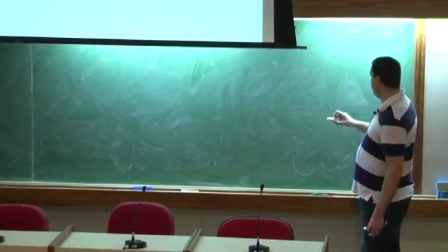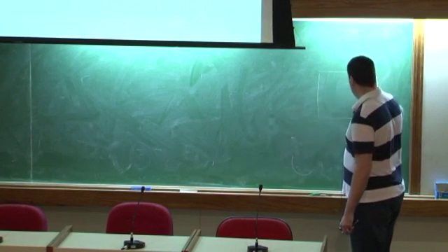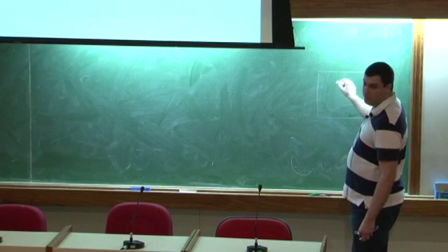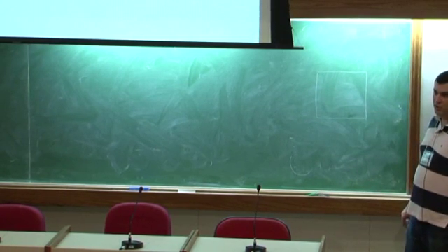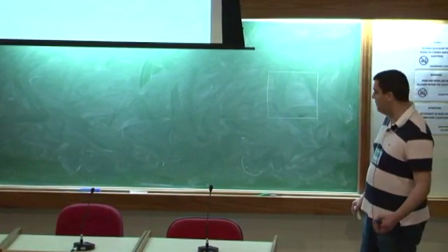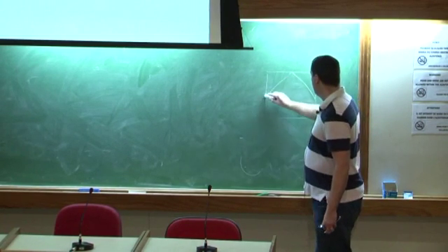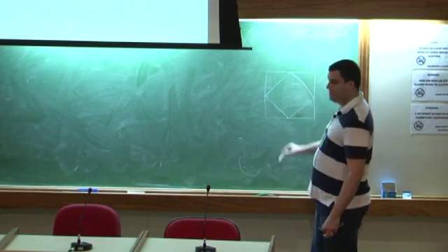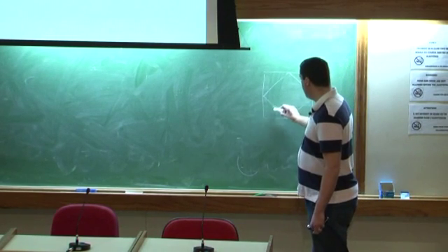What is a nested Fermi surface? Well, what I mean is that, suppose, for example, that I have the square lattice Brillouin zone. You solve the Hubbard model with U equals 0. It's just a hopping term. And you solve that for half filling. You find that your Fermi surface is just a square. This is the Fermi surface.